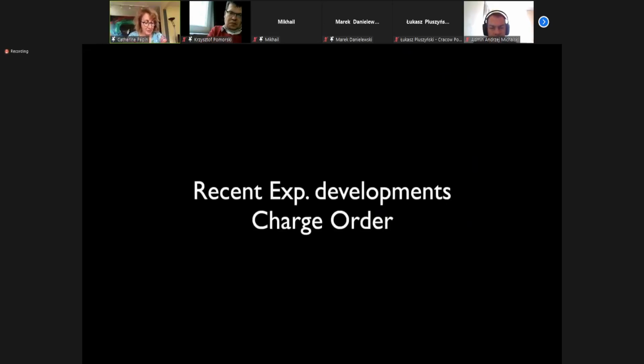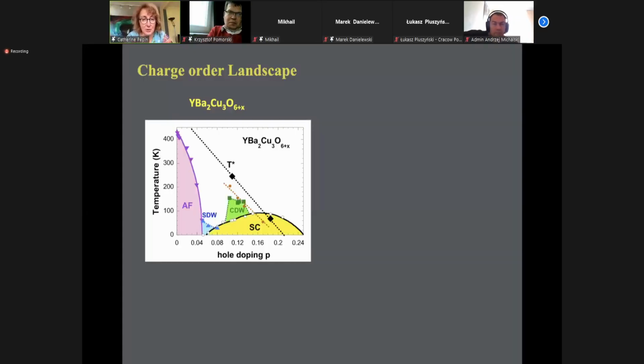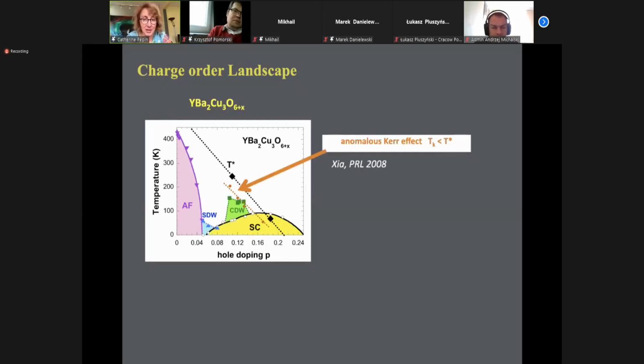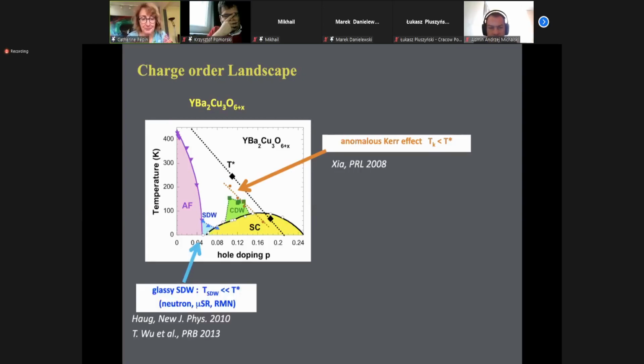So that brings me to recent developments here, which is the ubiquitous observation of charge order in the phase diagram of cuprates. Over the years, there has been a lot of experimental progress in these compounds, and the phase diagram has become richer and richer, especially below T star. There are a lot of discrete phase transitions, with anomalous Kerr effect, breaking time reversal symmetry, sorry.